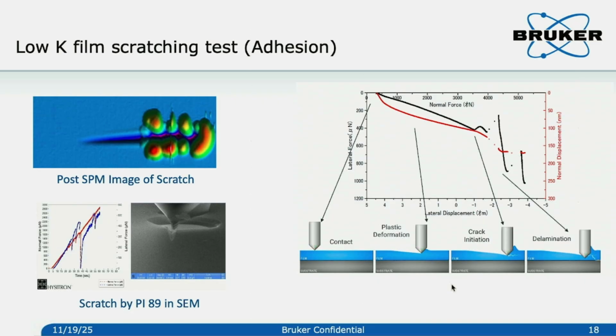Firstly, we have the contact, then plastic deformation of the material. Then you can see the first jump, that is a cohesive cracking. It's about the fracture toughness. So the biggest jump is about delamination. This will totally remove the thin film from the substrate. So in industry, they use the nano scratch to measure the thin film adhesion. I think our machine is already applied in the data storage or the semiconductor industry, to use our machine as the standard machine for the thin film adhesion measurement.